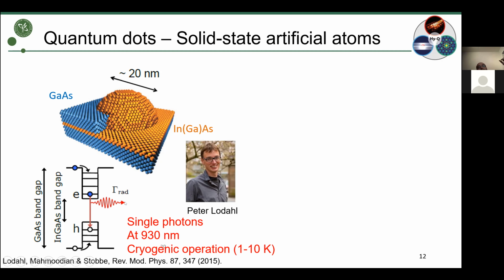So you typically have to cool it down, to remove most of this phonon background, and actually improve the quality of single photon emission. I would still like to mention that we're not talking about millikelvin, which is typically needed for some quantum technologies. Here you can live quite well with 2, 3, 4 Kelvin temperature, which is easily achievable in a normal helium-based cryostat, or closed cycle cryostats. So the kind of technology that allows us to operate quantum dots is actually improving a lot, and it's becoming more and more affordable.